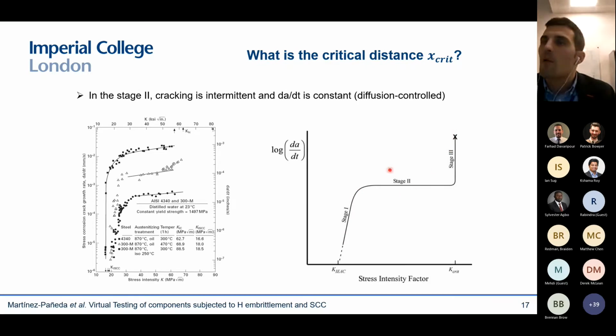And the reason why we have this second stage, you can see here in the experiments, is because at this point, cracking is diffusion controlled. So cracking occurs in a rather intermittent manner. So the crack is sort of jumping. And for the crack to do the next jump, the crack needs to wait for the hydrogen atoms to go from the crack tip or from the crack surface all the way to this critical distance.